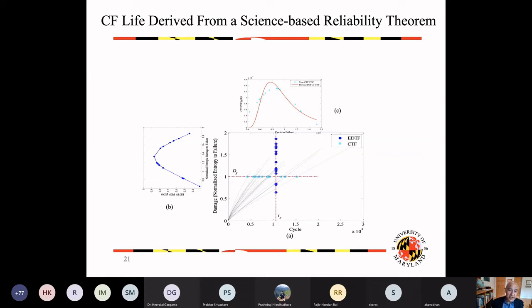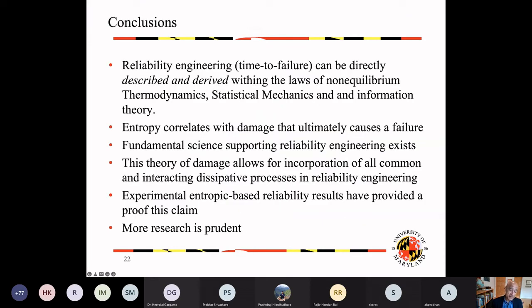In fact, if I fit a distribution to those data points, the differences between these two are acceptable from a statistical test of differences. The two distributions are exactly the same, which tells me that this distribution found from this is exactly the same as the distribution from observations of the failure.